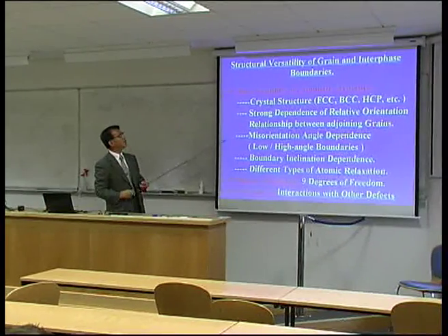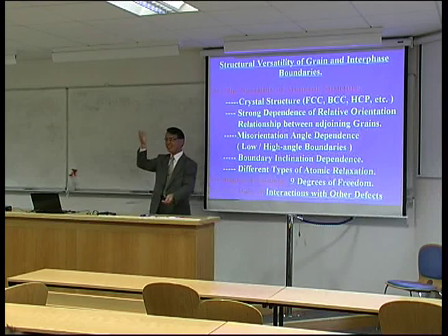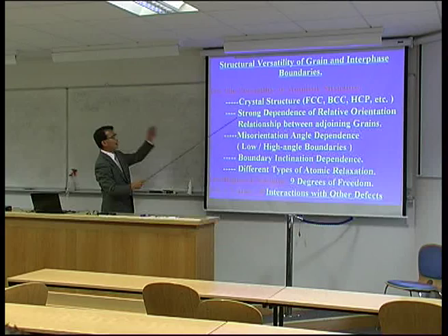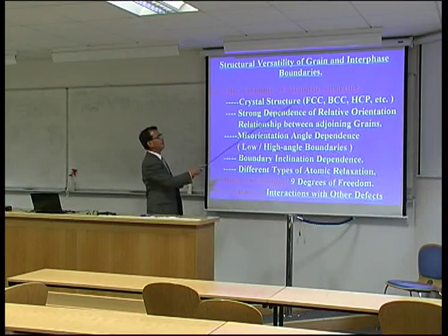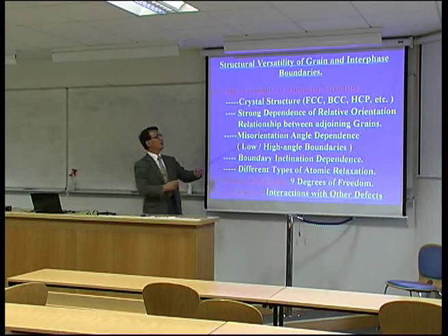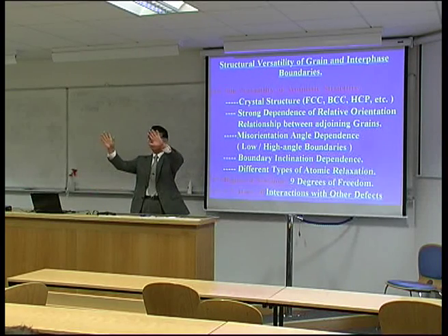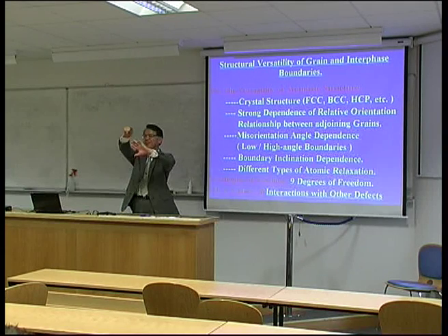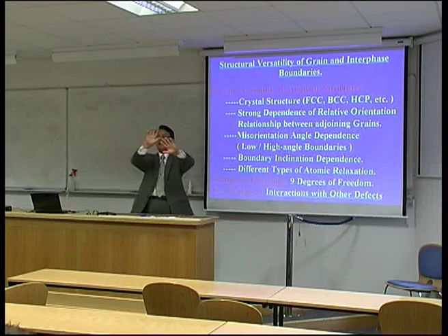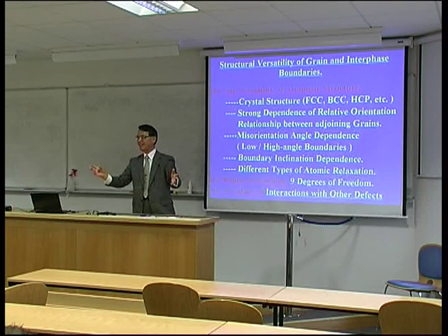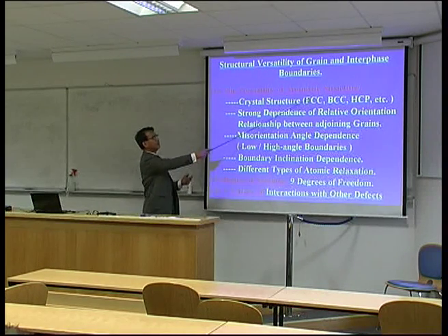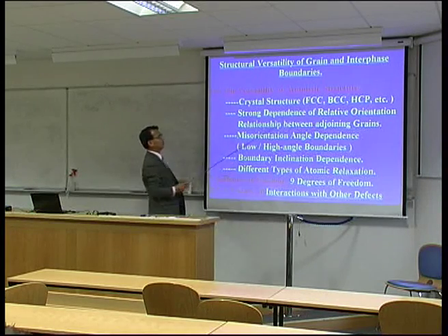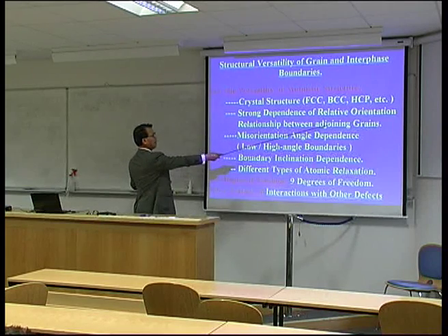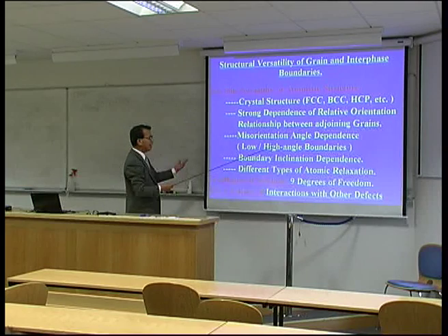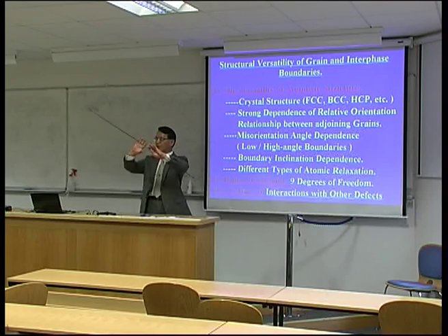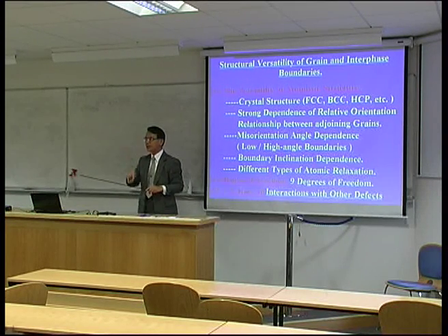But again, we really wish to know the atomistic structure of grain boundaries, not just the topological features. Even for single crystals, there are different crystal structures: FCC, BCC, HCP. So if a BCC crystal meets an FCC crystal, the atomistic structure of that interface should be different from a BCC-BCC grain boundary. It's very easy. So when we discuss the atomistic structure of an interface, firstly we have to think about crystal structure. And then, as I mentioned, relative orientation, the disorientation angle, whether low or high angle boundary. Even for a high angle boundary, depending on the rotation relationship, we can construct a very ordered structure.